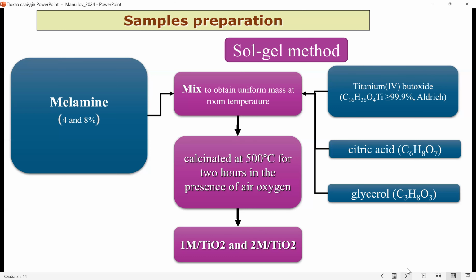For sample preparation, we used the sol-gel method for the undoped titanium dioxide preparation. The titanium butoxide, citric acid, and glycerol were mixed to obtain a uniform mixture at room temperature and further calcined at 500 degrees centigrade for 2 hours in the presence of air oxygen. The samples of melamine-doped titanium dioxide were obtained using the same mixture, but with the addition of melamine, 4 and 8%, before the heat treatment. After cooling, the powders were triturated until smooth. The 4 and 8% melamine-doped titanium dioxide samples were labeled as 1M TiO2 and 2M TiO2, respectively.